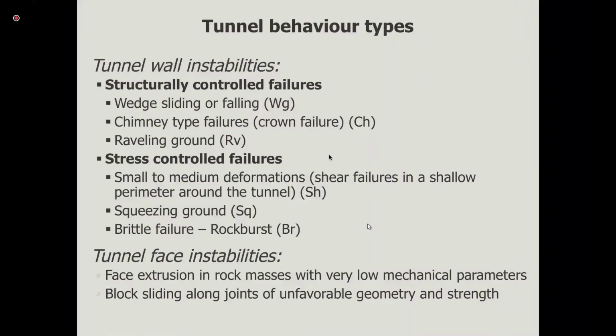So we can identify the structurally controlled failures and wedge sliding or chimney type failures or crown failures you may find in the literature, raveling ground or flowing ground. And there are then the stress controlled failures of small to medium deformations. So we have shear failures in a shallow perimeter around the tunnel. And squeezing ground, of course, is the more severe expression of these stress controlled failures. And of course, the brittle failure and the rock burst or spalling we may have. And the tunnel face instabilities, of course, again, we may have face extrusion in rock masses with very low mechanical parameters at depth, and block sliding along joints of unfavorable geometry and strength.